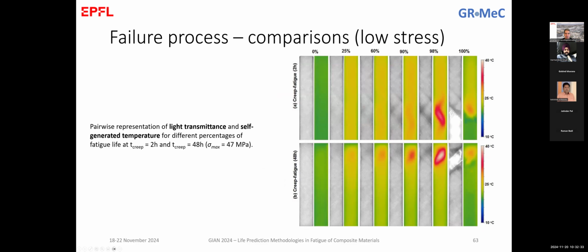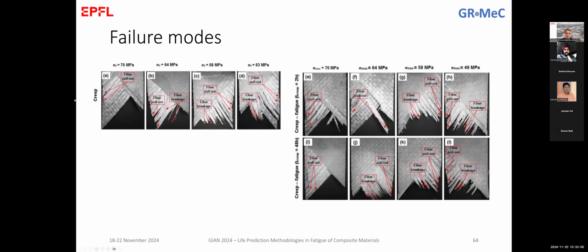The same comparison is shown for a different material at low stress levels, where again, because the creep stress was not significant, and it was necessitating very, very long times for failure, in both cases we observed fatigue failures. And again, discussing very briefly the failure modes, photos taken with the same handheld microscope, we can see similar behavior to what we observed before with fiber pull-out and fiber breakage, especially the combination or the dominant fiber breakage comes to the specimens that are loaded at lower stress levels, exactly as we've seen before. And when we are at high stress levels, we mainly have fiber pull-out.